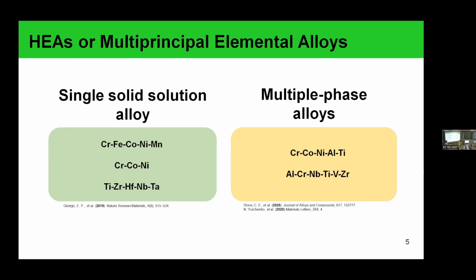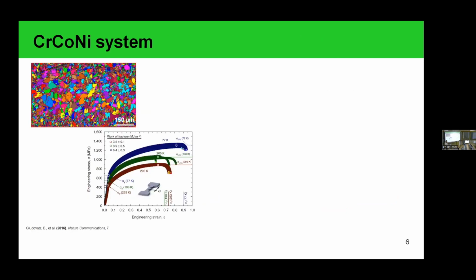So in our study, we are focusing on these alloys, which are called the Cantor alloys family, since they contain in their composition chromium, cobalt, nickel, and other elements. And considering the properties of this 3-component system, we see that this material has really good strength characteristics at cryogenic temperatures, and it demonstrates higher strength characteristics in comparison to the 5-component system at room temperature.